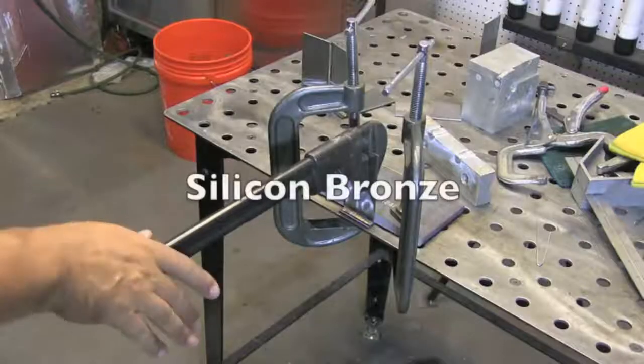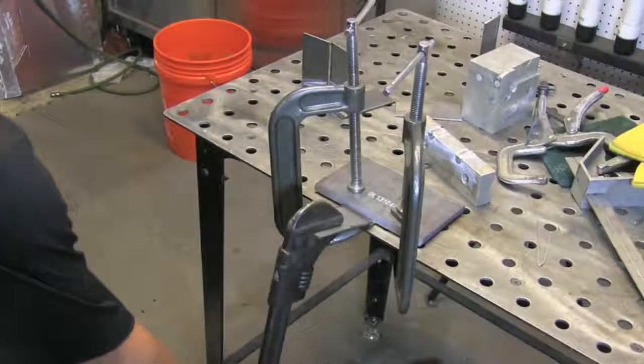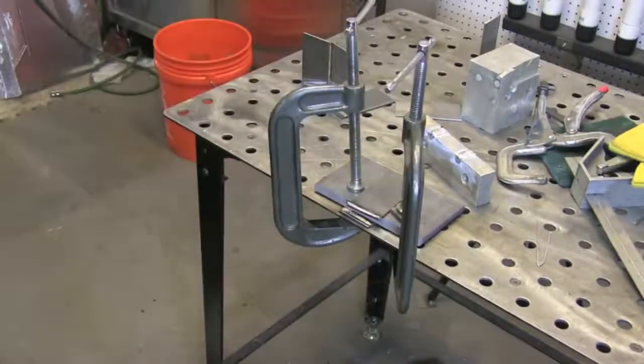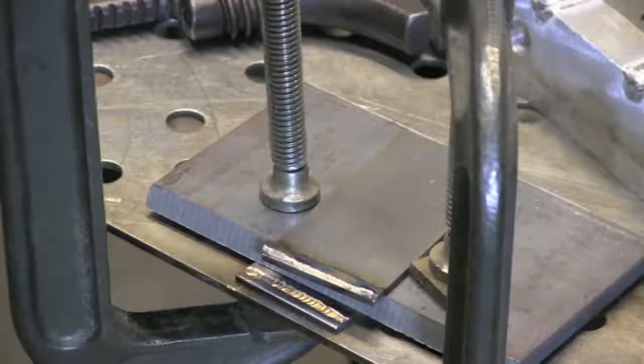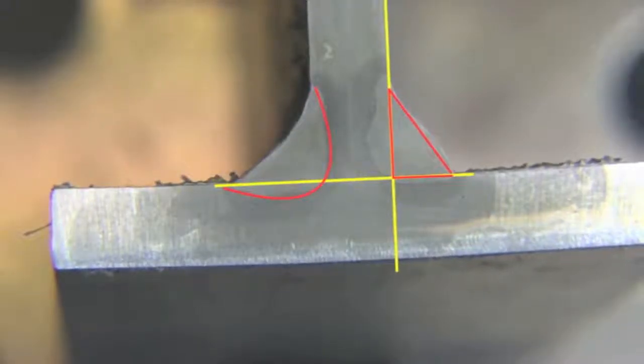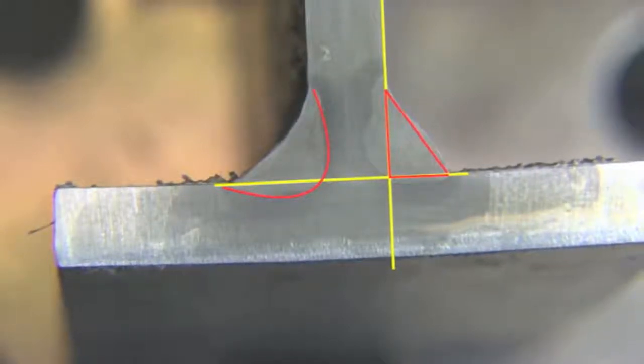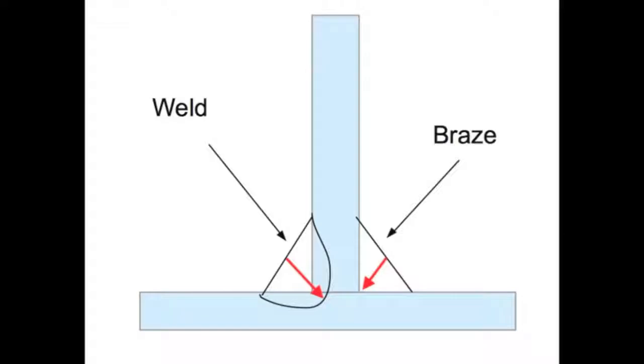We'll cool that off and then put it in the same situation. Very easy to snap. Even though I think the fillet is slightly larger than it was with the weld metal. But there's a pretty good reason for that. The silicon bronze, like I said, much weaker on tensile strength. But also, if you take a look at the difference between a weld and a braze, on the left you got a weld, you have some penetration there. And on the right you have a braze, basically a triangle. And it winds up being much less of a throat, much less of a cross-sectional area, and it just doesn't lend itself well toward a single-sided joint like that. It needs to be welded on both sides for it to have a lot of strength.